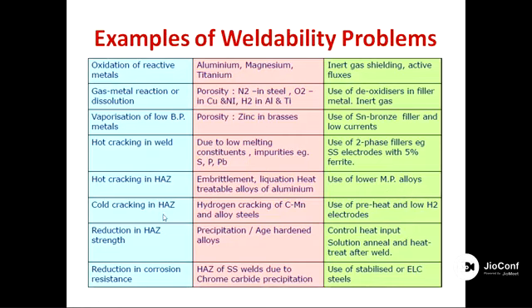Then there will be cold cracking in the heat affected zone, particularly in carbon, manganese, and low alloy steels. Because of the hydrogen, when the hydrogen diffuses into the welded carbon, manganese, and alloy steel, this hydrogen can crack. And the remedy to this problem is the use of preheating, so that the hydrogen can be removed, post-weld heat treatment, and low hydrogen consumables, or using electrodes that have very low hydrogen content, right? This is known as low hydrogen practice.